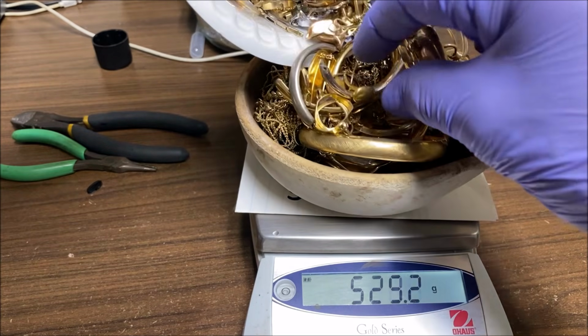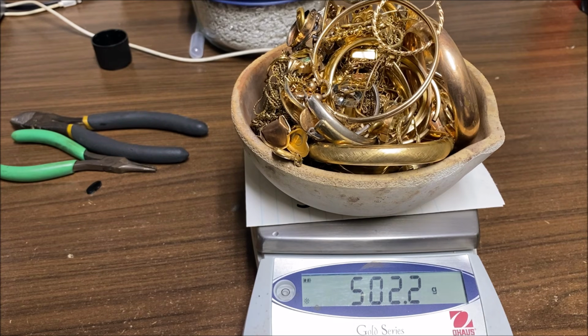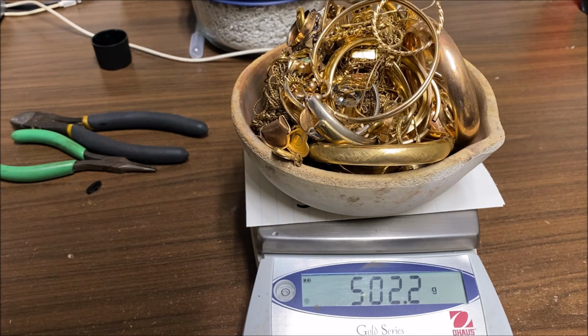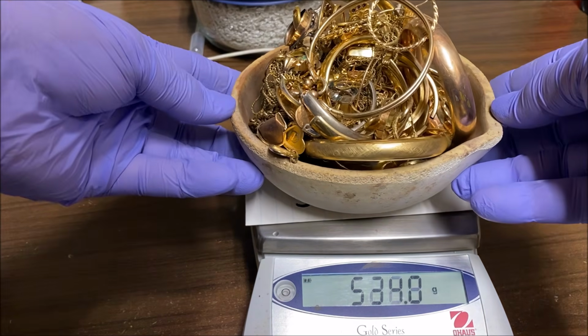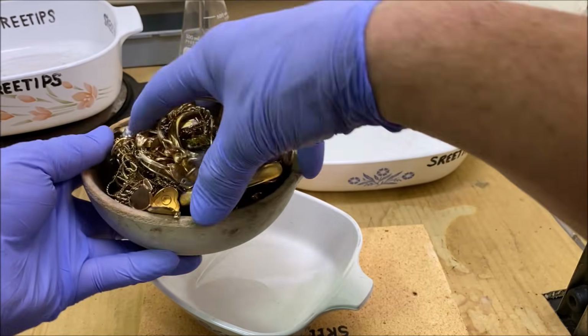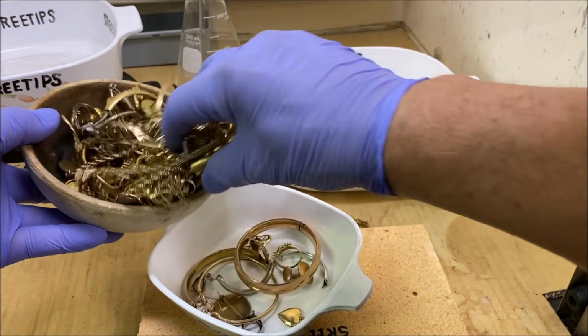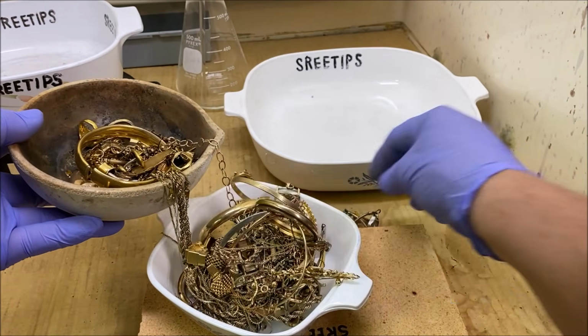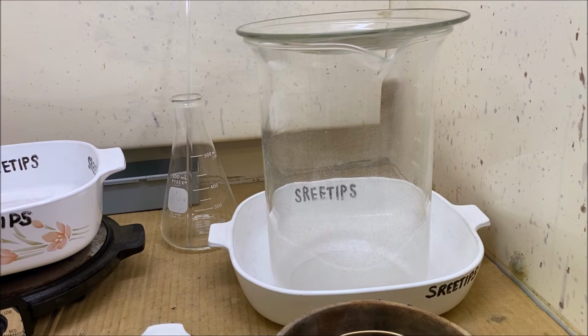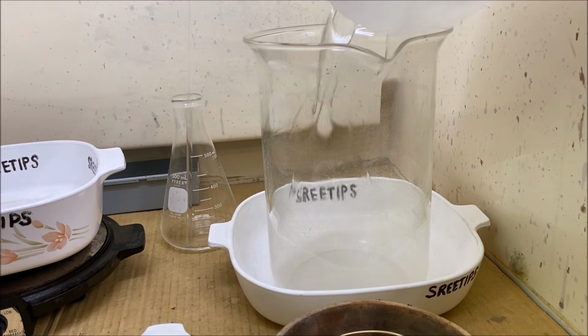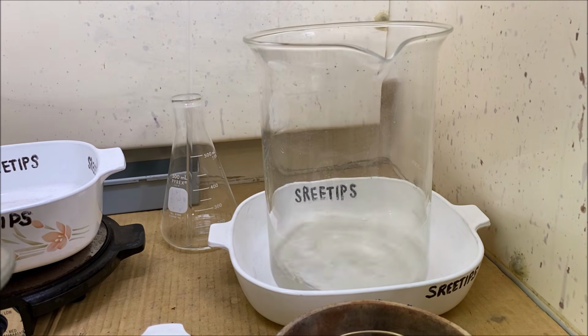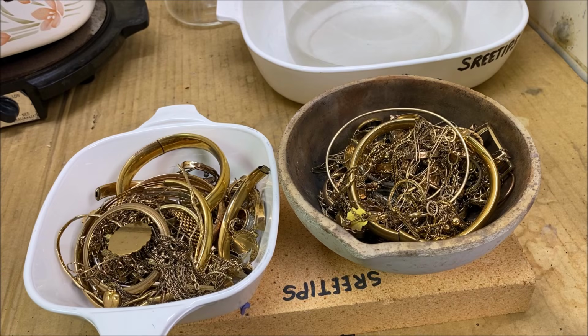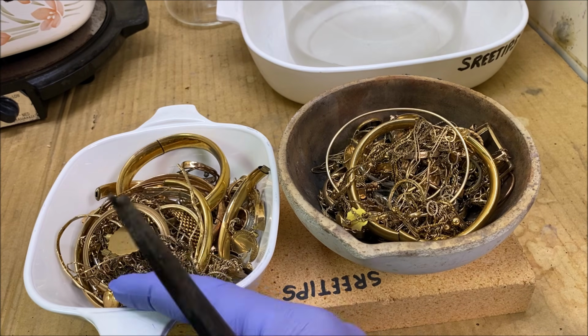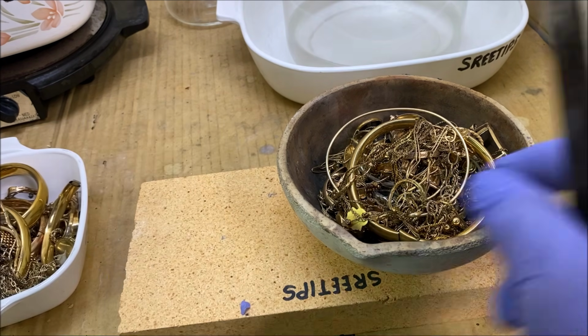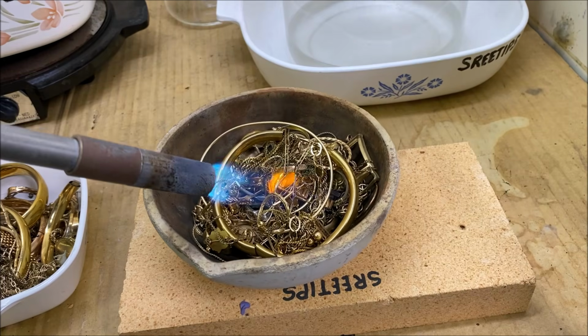Incinerate the gold. All right, we got 529.2 grams of gold filled scrap. I'm gonna take it out here now and we're gonna burn it. Here we go. Take some of this out of here. The pan's too crowded to try to burn it all at once. I'm gonna start this off by adding some distilled water to a clean beaker. I've split the gold-filled material into 2 groups so that I don't crowd the dish.